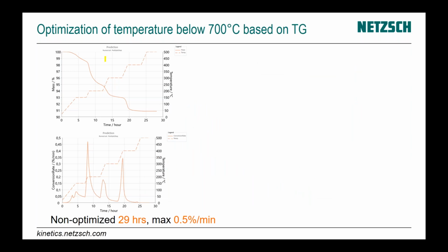How it works: here are the original non-optimized temperature profile, and here we have a debinding or decomposition of polymer for non-optimized temperature profile. It is relatively long. If we calculate the first derivative, then we see that there are some spikes, and these spikes mean a too intensive decomposition of polymer, and exactly at this point there could be decreasing of the quality of our material.